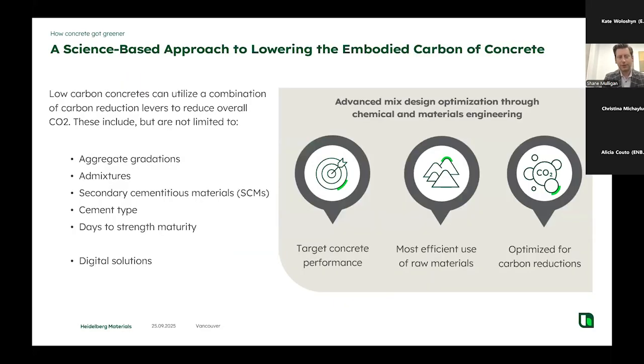The way that we deliver these carbon reductions is really about materials engineering principles, and our technical service teams are generally looking at the different levers that are at our disposal to help reduce the carbon impact of the concrete matrix as a whole. That involves looking at the aggregate gradations to get better particle packing and more strength out of the aggregate structure in itself, which helps to be able to pull out some of the cementitious content that might be going into that concrete.